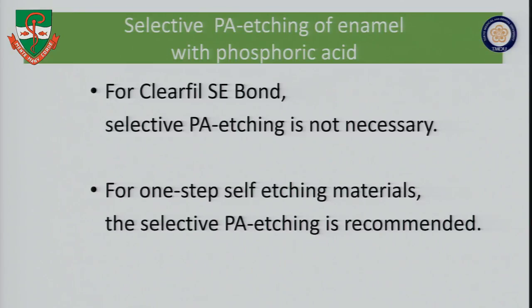So that's why we understand that for Clearfil SE Bond and another kind of two-step self-etching material, selective phosphoric acid etching to enamel is not necessary. But in the case of one-step self-etching systems, for most of them, the selective etching is recommended.